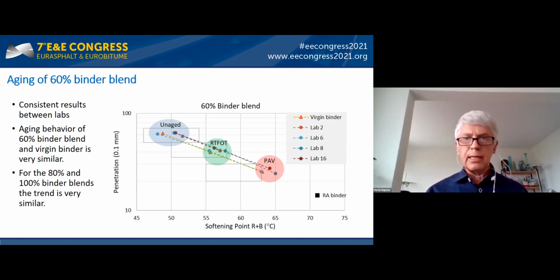So you see here, as an example, the 60% binder blend, and actually it's quite the same result as with the 80% and 100% binder blends, so I don't have to show them all. You'll see clearly the virgin binder, how it's aging like before, and the results of the 4 labs which did perform this testing and aging. And it's surprising that the results are quite consistent. They are in parallel to the aging, so the aging is really the same as the virgin binder.